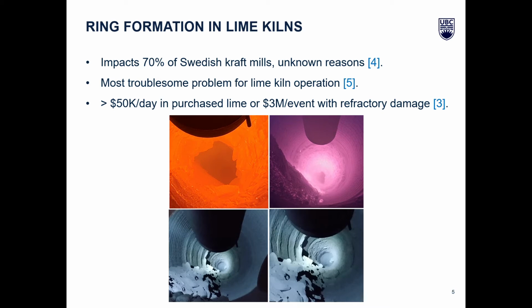Ring formation is described in literature as the most troublesome problem for lime kiln operation. A survey of Swedish kraft mills indicated that over 70% suffered from ring formation, and most did not know why. Rings can choke off a kiln, costing upwards of $50,000 per day in purchased lime, and in some bad cases, rings can cause damage to the shell or the refractory that can cost over $3 million per event.